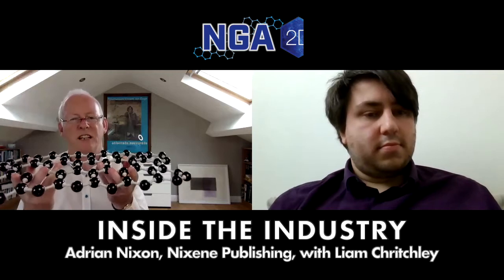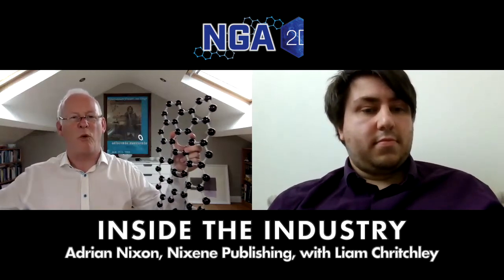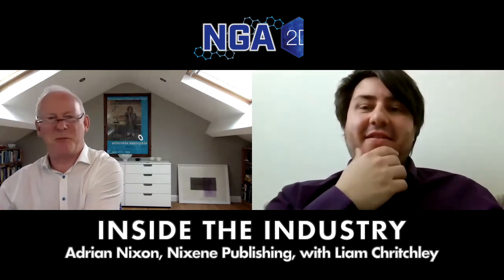And when they ran the calculations, they found that with helium and everything upwards, graphene is the most impermeable material ever tested. And the researchers calculated that a single atomic layer of graphene is equivalent in permeability to a kilometre thick wall of glass. That's quite impressive. Yeah, and that's just two, well, three of the bits of the latest research that have been going on this year.